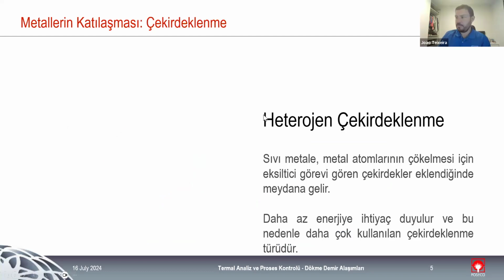And we have two main types of nucleation of stable nuclei. We can have a heterogeneous nucleation. This is what we are trying to achieve with the use of inoculants. So basically, we are giving the liquid metal the stable nuclei for the nucleation to start. So basically, what inoculation does to the liquid metal is adding points of solidification for the stable nuclei to start to grow. This way, it's less energy consuming, and we can achieve a solidification in less time than if we don't have any type of inoculation.